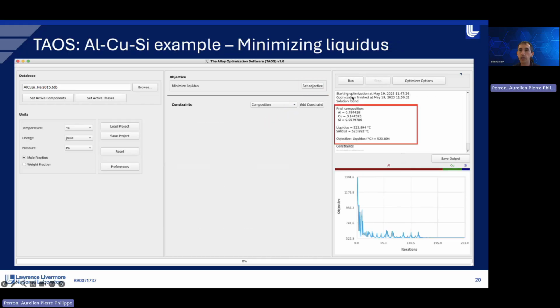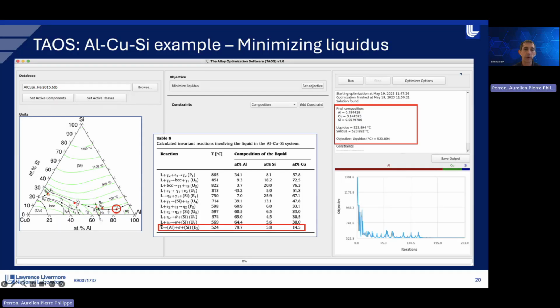Then you just have to click the run button and you will have here, for instance, the output of the optimization. It will give you the alloy composition and the liquidus and solidus temperature. And our objective was minimizing the liquidus. You can also, if you look at live, have an evolution of the optimization and it will track the different alloy compositions that were tested. So if we go back to our initial example from the literature, we can see that we can indeed minimize the melting temperature in this alloy.